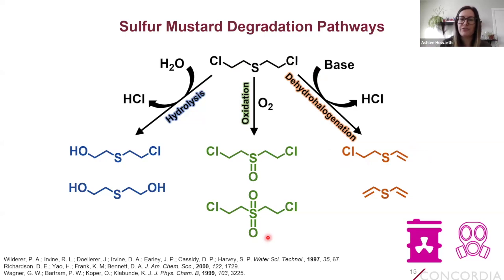And so we choose to focus on the oxidation pathway, where we can just use molecular oxygen as an oxidant to do this, which is great. But you have to be careful here as well, because the oxidation has to be selective to generate the sulfoxide. Because if you over-oxidize this compound and you generate the sulfone, you end up with a compound that's nearly equally as toxic as mustard gas itself. And so selective oxidation is key for detoxification.